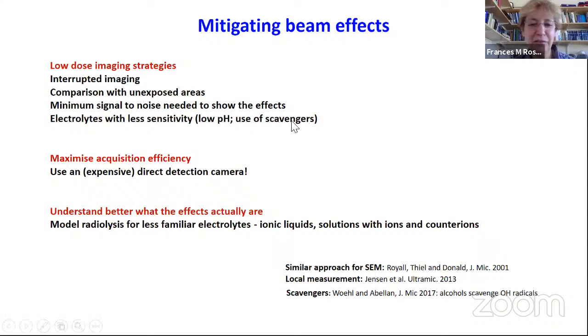You can use chemical scavengers to reduce the effects of the radiolysis products. And if you have a choice, choose electrolytes that are less sensitive to the beam. Of course, count every electron, use a direct detection camera, but those are expensive. But if you can find a microscope that has one, you're in better shape. And then we need to do a lot more modeling for less familiar electrolytes, including if you add a whole load of ions into the solution, how do they change radiolysis? What happens with ionic liquids? So there's a lot of work going on here. I've just cited a few of the papers that I've found useful over the years, but this is a very active area, and for every experiment you've got to think about the beam